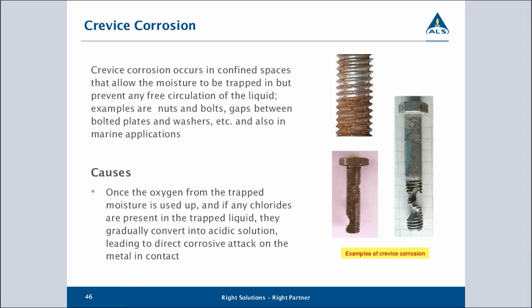Crevice corrosion is very similar to what I was talking about with pitting, where you get corrosion starting at a point and it just keeps driving through. Of course, we tend to notice this more where we've got water trapped in an area that it shouldn't be trapped, and that's the examples they're showing on screen with bolts and threads that have been eaten away, just to illustrate what can happen. But it can potentially happen in a cooling system if we've got a blocked area where we've got a small content of water or fluid trapped, and then this crevice corrosion type action can start up and eat through something. And it can eat through pretty quickly, so it doesn't take very long for this to punch a hole in something.